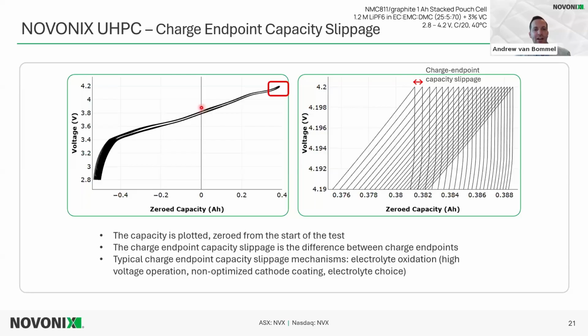Here's a different way of plotting that graph. Starting at the start of test, we were at 3.8 volts. So there's charge of that. After this step, there's the charge at C/20 and the discharge. So this completes 25 times. And we could see that that charge endpoint is walking along.